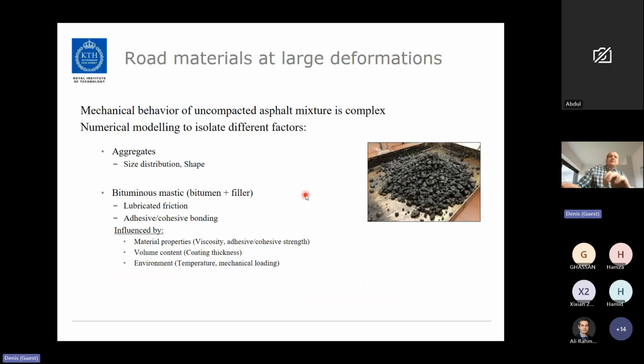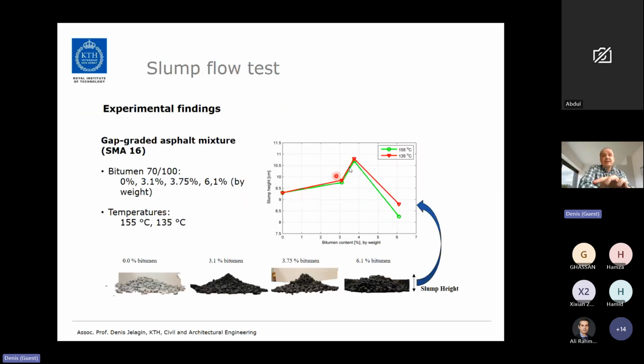And for a while, this means that slump height starts to increase. Higher slump means less resistance to flow. But then at some point, when binder content is high enough, it reduces friction between aggregates significantly, and this means that slump height drops quite a bit. This is also when we start to notice the effect of temperature very obviously on our results. So here you have two lines at 135 and 155 degrees Celsius measured.